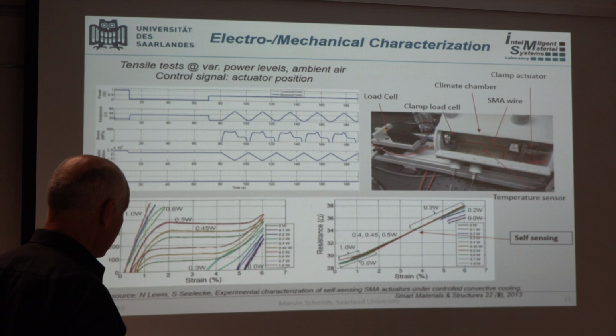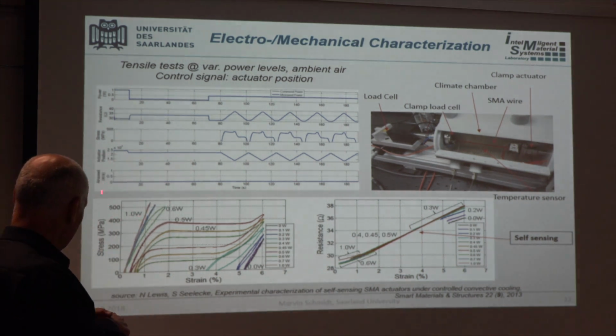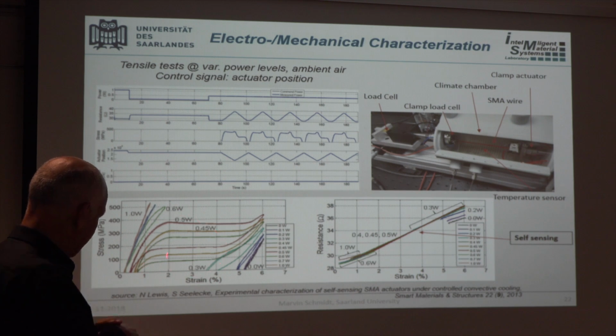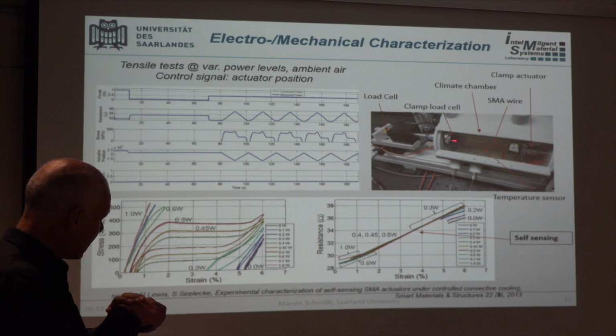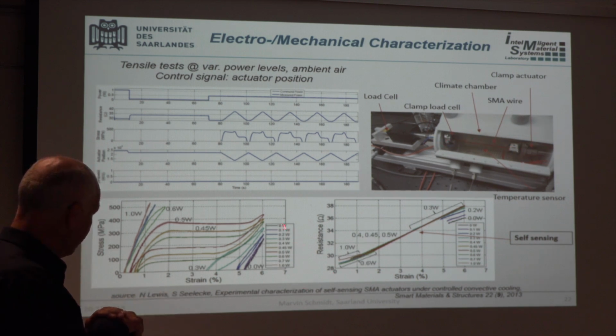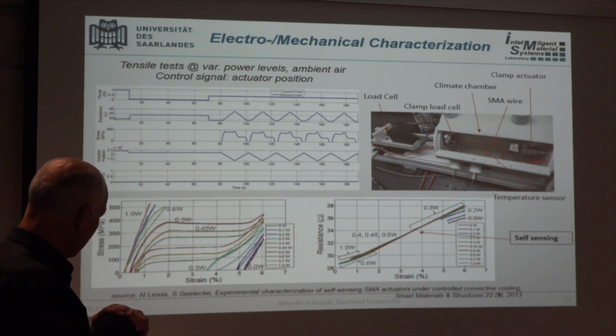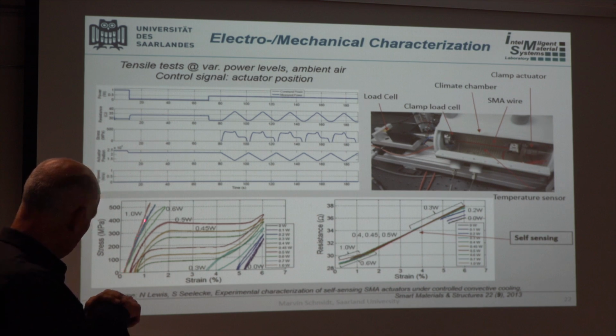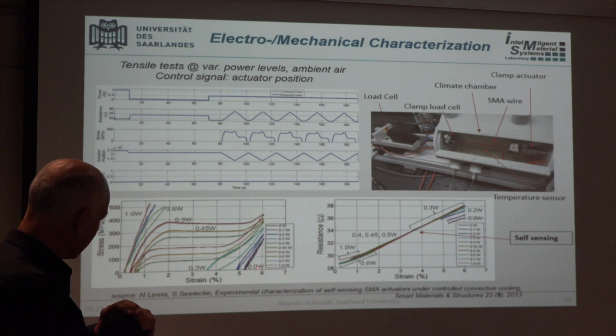The only thing I really want to show you here is that you do a characterization in order to get an idea of the stress-strain behavior. And that stress-strain behavior depends on the temperature or on the electric power that I apply to the wire. So we run a lot of tensile experiments under fixed powers, and you see that at 0 power it moves up on what we call the martensitic branch over here, and the more power we input, the behavior changes so that we have a large hysteresis for medium power levels in between, and when we go to very high power levels we move up on these branches. This is where the material is in the austenite, here's where it is in the martensite, and in between that is the range that we use for actuation.